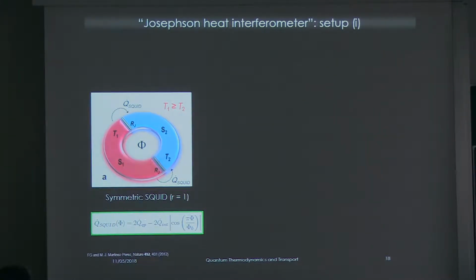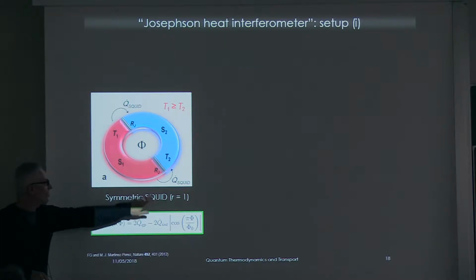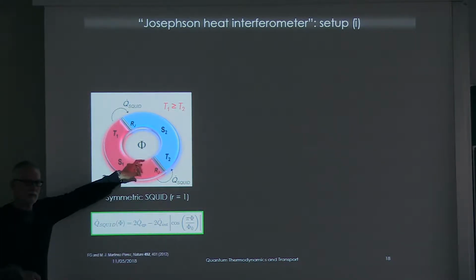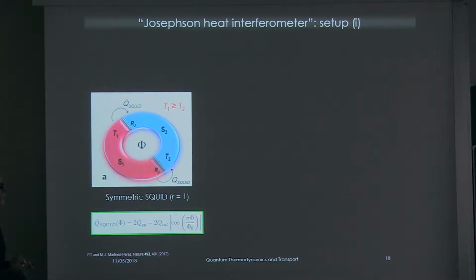So the total heat current is twice the quasi-particle part minus twice the interference part, let's say. The minus means that it can be immediately interpreted in an anthropomorphic way, saying that the interference part is flowing in the opposite direction with respect to the thermal gradient. So this is very interesting. For phase equal to 0, you see that it is flowing from the colder to the hotter. Of course, we are not violating the principles of thermodynamics. So the full heat current will always be positive and flowing from the red to the blue.